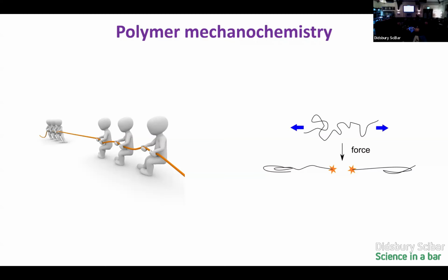And if we think about that again, we look at our polymer. I'll go back to the thread one if I can get you to. Okay. So if we have our random coil, we start to pull it out and pull it out and pull it out and pull it out. If we really pull it, what we can see is that tension builds up along this thread, and actually where the tension is going to be highest is at the middle point of this thread here. It's not going to be that high here. It's going to be all the way in the middle where we pulled it really, really far. And this is where the bond is likely to break, okay, if we stretch out our polymer chain like that. So if we pull them far enough, fast enough, with enough strength, we can cause these bonds to break.